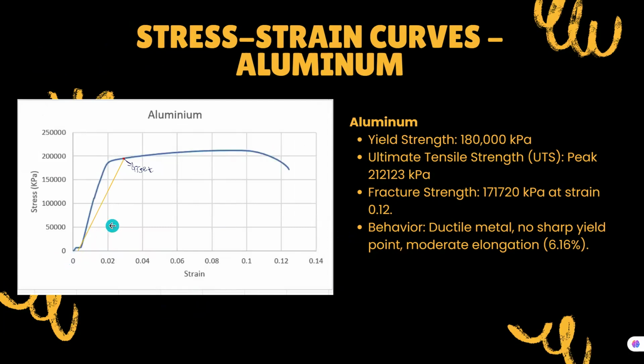And then next, this is for aluminum. Using the offset, we also get that the yield strength here is 180,000 kilopascal. And for the ultimate, the highest point is at 212,123 kilopascal. And for the fracture, the end of this line is 171,720.